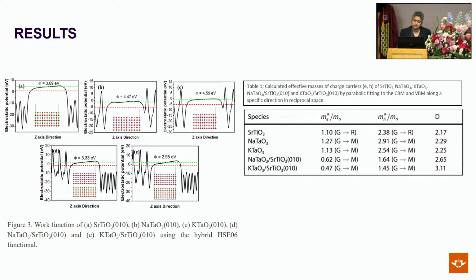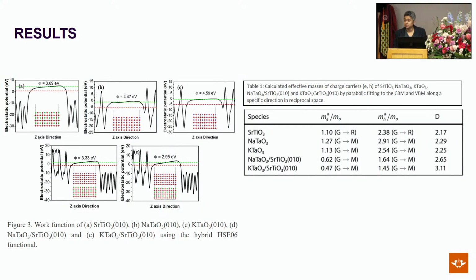To complement this, we did some calculations on the effective masses of charge carriers, which means the electrons and the holes. What is important here is the D value. The D value is the ratio of the electrons to the holes. And the higher the D value, the lower the recombination rate and the greater the photocatalytic activity of your material. As you can see, it is the heterostructures that have the largest value. So it means that this material is highly active.